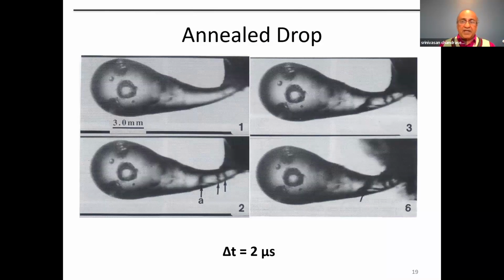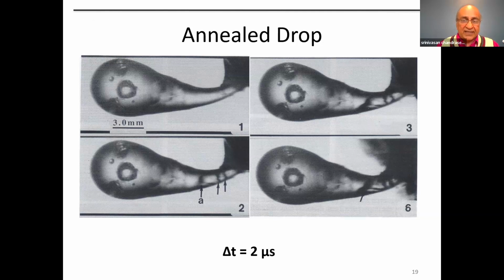Now, we also did some experiments taking a Rupert's drop and then annealing it. Annealing means we just heat it to a suitable temperature, in this case, something close to the glass transition temperature. And what annealing does is it gets rid of the internal stresses in the glass. So somebody asked the question, I think early on, whether we had done any work with annealed drops. And so this is an annealed drop. And again, the same crack, explosion from the tail. But here the drop doesn't disintegrate. Instead, it just breaks into 2 pieces.